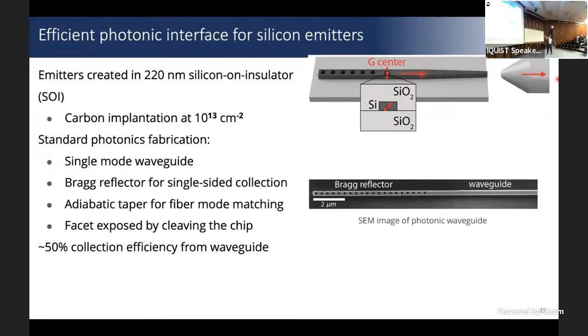This defect creation process is actually pretty complicated. We don't fully understand it, but it works well enough for what I'll show today. And then we do standard photonics fab. We do lithography to design and etch these silicon photonic structures. At the end of the day, if you have this quantum emitter inside your silicon photonic waveguide, you can collect the photons emitted into a single mode fiber with about 50% efficiency. In our simulations, it's about 70%, but in the lab, we regularly get about 50% or so.